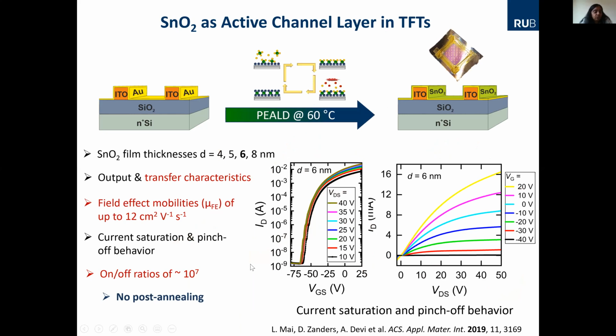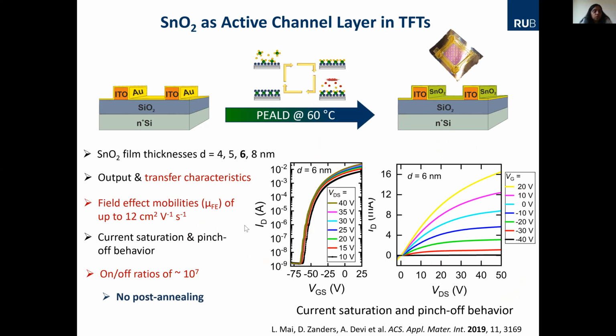Now, finally, the application was to see, can this film be used for TFTs as a channel material? So the engineers made a TFT structure where you have heavily doped N-type silicon, then a thermally grown oxide, and then the top electrodes. Before that, we coated the tin oxide by ALD. That's the process we use at 60 degrees centigrade.